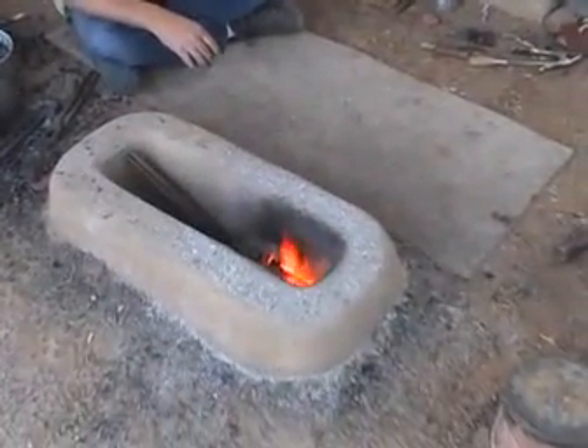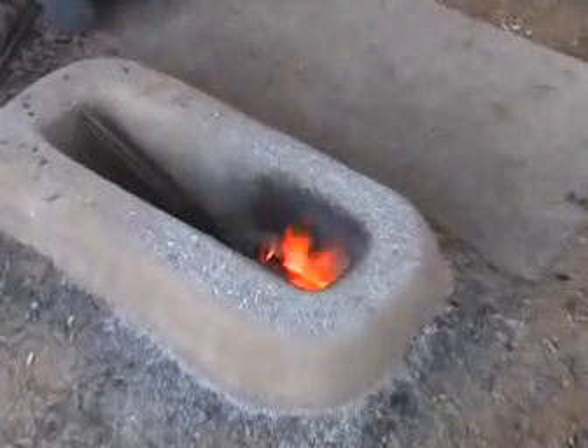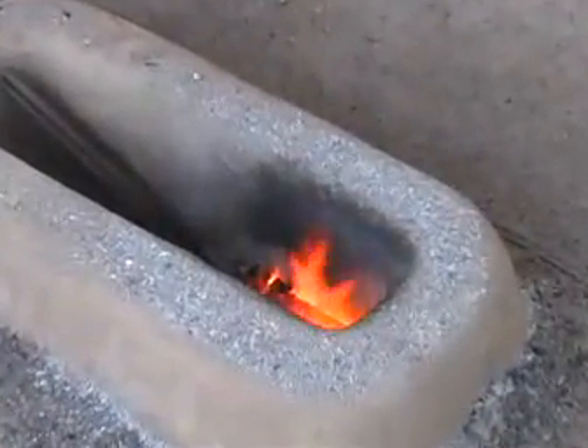There are 3 basic steps to the heat treating process: annealing, quenching or hardening, and tempering. Annealing, which we've already done, is to soften the metal and get all the stress out of it that we've hammered into it. Now we're going to go to the quenching or hardening step. I heat the blade back up to non-magnetic, nice and even, and I quench it in the automatic transmission fluid, and then after that we'll temper it.